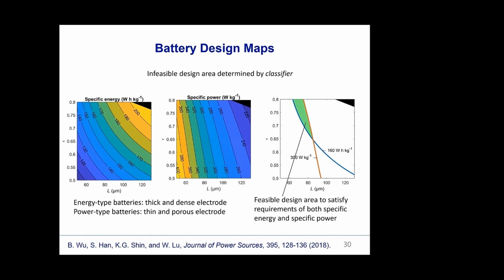This figure shows the design map for the two most sensitive parameters, electrode thickness and volume fraction of solid. Thick electrode and a high volume fraction of active materials lead to high specific energy but low specific power. The contours can be combined to fulfill both requirements of specific energy and specific power. The green area denotes the feasible region where the specific energy is larger than 160 and the specific power is larger than 300.